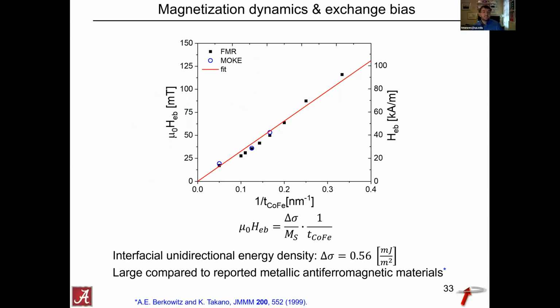What do you get out of this? Well, once you do these angle-dependent measurements, you can more precisely determine the bias field here. And then you can do that again for a whole bunch of different samples. And with a little bit of goodwill, you can fit this to a straight line. And from that, you can extract something that's very interesting for applications, which is the interfacial unidirectional energy density.